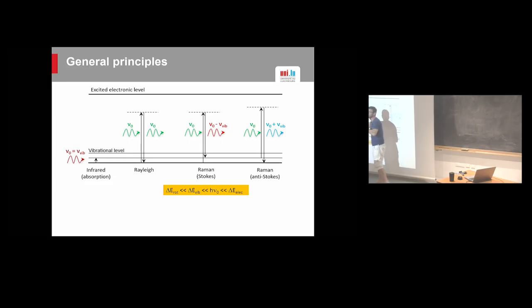So again, important thing here is to remember this underlying assumption that we are working with visible light, it's well above the vibrational levels, and ideally below any real excitation. So if you're talking about a, say, high band gap material, like our classical ferroelectrics, it works. But of course, if you're talking about strongly correlated systems with a much lower band gap, this is an approximation that's very disputable.